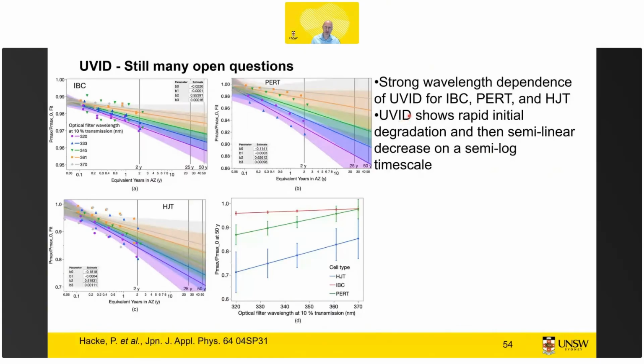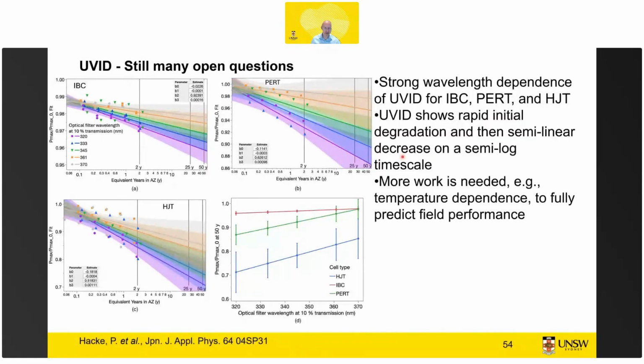But there is strong wavelength dependence, which we have to further understand. There are also two stages of degradation. You see first rapid degradation. Details are in the paper. What Peter shows here is this second phase, which is a bit slower, scaling on a semi-log plot, which means you really have to look at every doubling. You have an equivalent decrease, so the degradation really slows down in time. You have rapid degradation at first, and then the relative increase from 2 to 4 years is the same as from 10 to 20. So it's a problem that scales quite slowly. But definitely more work is needed, and we have some results in the lab that show there's probably another phase after, a recovery phase, in addition to the degradation phase. So hopefully, if that kicks in, this picture would look even better in terms of degradation.